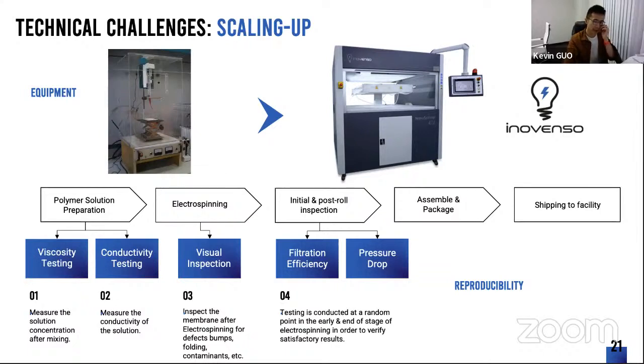The second limiting factor is the reproducibility of nanofiber products. Due to the large number of variables in the electrospinning process, it's really difficult to control the consistency of the nanofiber product. Based on our own experience, over 90% of the inconsistency of the product comes from the solution preparation steps. In that case, we have implemented rigorous material inspection and SOPs to help us address these issues.